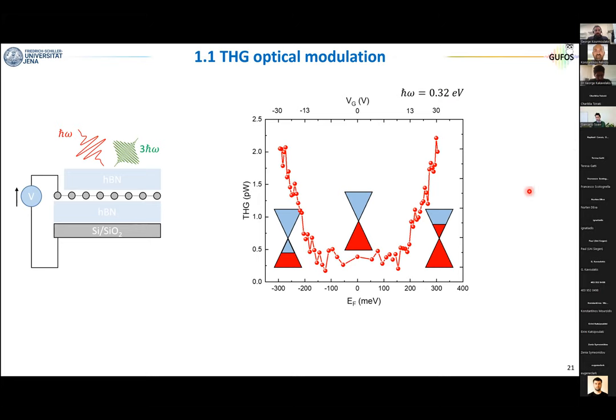Now I go back to the question of George. You see now the silicon dioxide is much thinner, it's 90 nanometers. So here we apply gate voltages of around plus minus 30. The graphene is encapsulated, so at zero gate voltage the Fermi energy lies at zero, the material is undoped.